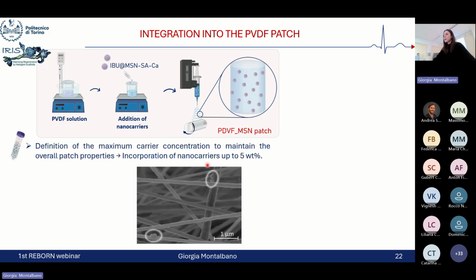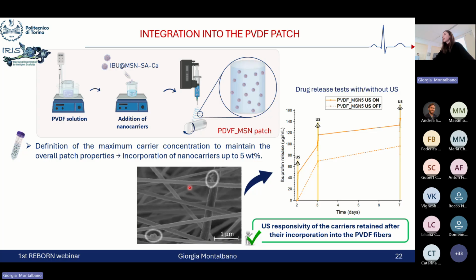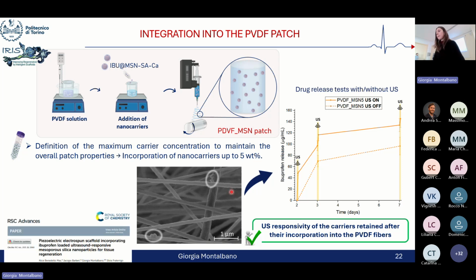During the optimization of the procedure, we could define the highest concentration of nanocarriers in the system that could maintain the overall patch properties in terms of morphological features as well as mechanical and piezoelectric properties. And then the release test performed on the patch sample with and without application of the ultrasound could also confirm the preservation of the ultrasound responsiveness of the carriers also after their incorporation in the polymeric fibers.